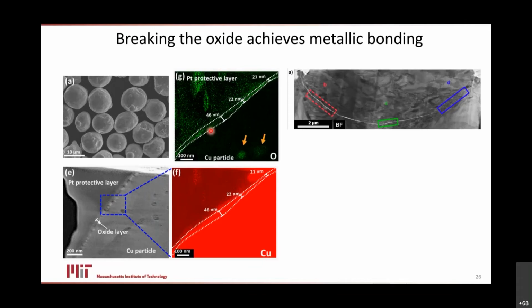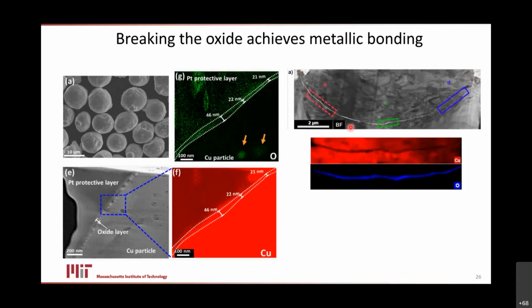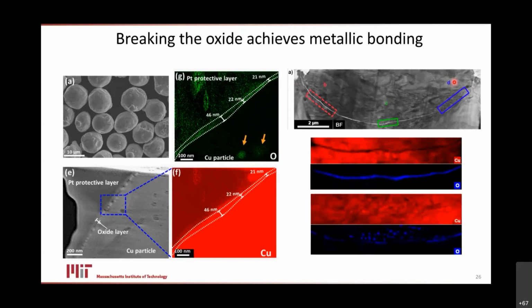And here's what it looks like after we shoot these particles into the substrate. Here is the particle, and the substrate is down underneath. If we cut these open and look at the interface, we can see how important the oxide is, because some portions of the interface are not bonded at all. The particle and the substrate never meet; there is no contact of the copper metal, because the oxide has remained in the middle, fully present and preventing metallurgical bonding. Whereas on the other side, we have higher deformation: we've broken up that oxide, rarefied it, and we have metal connecting all the way through the interface. So this particle is tacked on only by virtue of a little patch on the right-hand side.